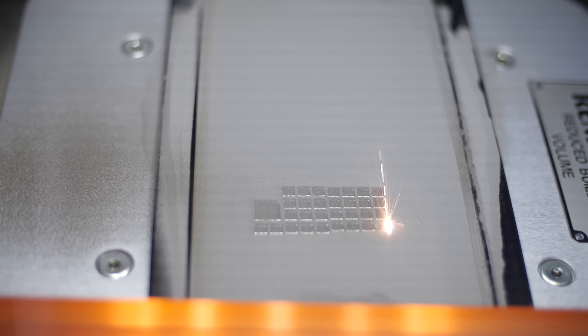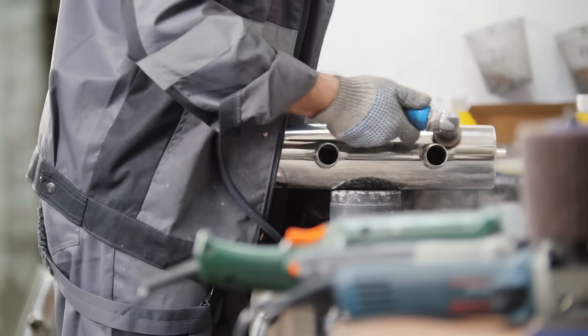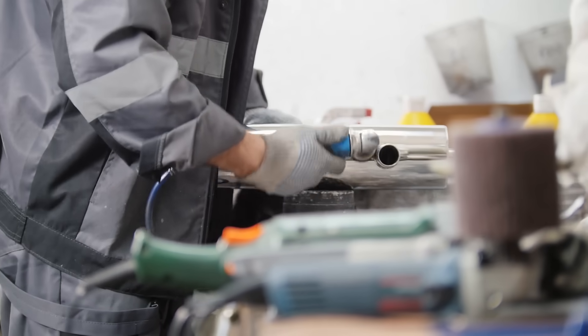As the laser moves across the powder bed it melts it, essentially forming a weld line. You can see that this layer tended to dig into the powder bed, creating a track that varies in height. These sort of imperfections means the final product needs a surface machining to create a quality part.